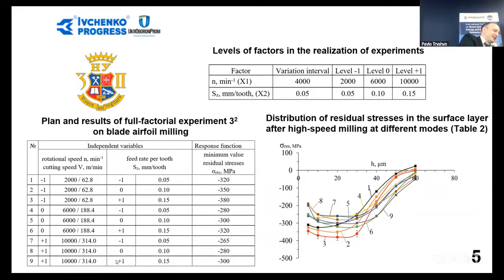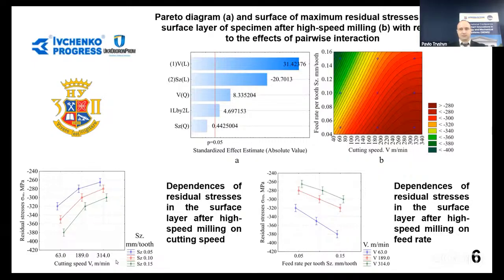The diagrams of residual stress distribution in the surface layer after high-speed milling with the different modes showed that in the investigated range of cutting modes, compressive residual stresses were formed in the surface layer. The maximum value of residual stresses was observed at a depth of 25 to 35 micrometers from the surface, didn't depend on milling modes, and was about 260 to 350 megapascals. The analysis of variance of the active experiment results allowed us to study the influence of cutting speed and feed rate per tooth on the value of residual stresses. It was found that the investigated cutting modes, as well as their interaction, had a statistically significant effect on the value of residual stresses.